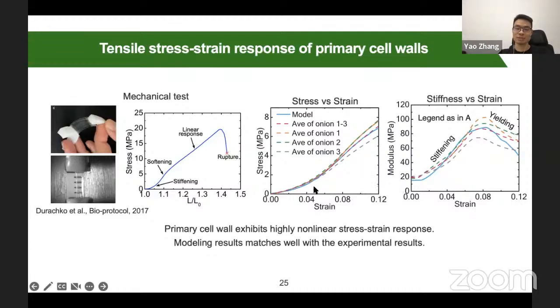In this modeling strain range from 0 to 0.12, our modeling result matches the experiment result. And also, if you look at the modulus, it has the same trend. At the beginning, the modulus will increase and then it will decrease.